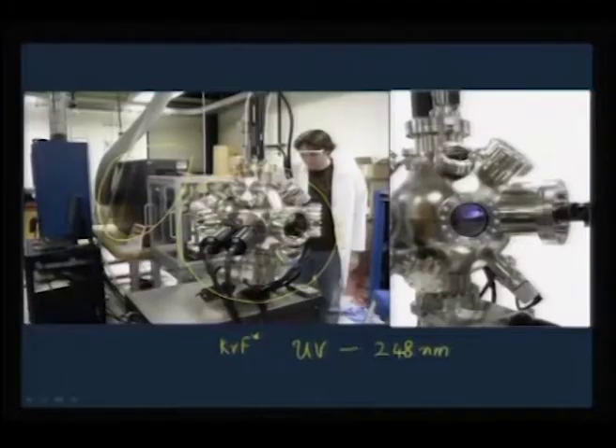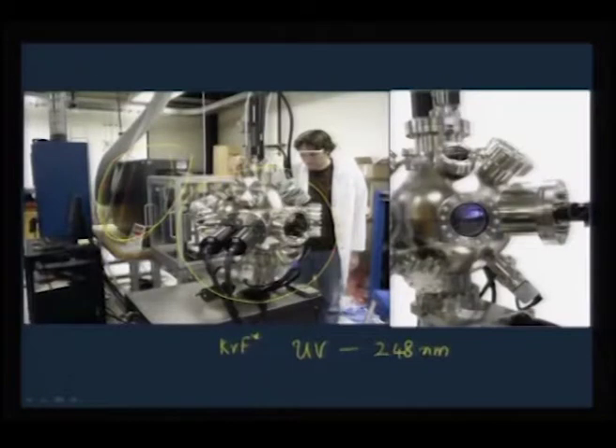In any PLD lab you would see the vacuum system, then the optical arrangement bringing the laser light into the vacuum chamber, and then of course the laser. Typically when you are trying to do the reaction, during the PLD deposition you would see some sort of a flash like this, which means the plume is coming with very intense colors, and the color can actually tell you whether you are really depositing the right material under the right conditions or not.